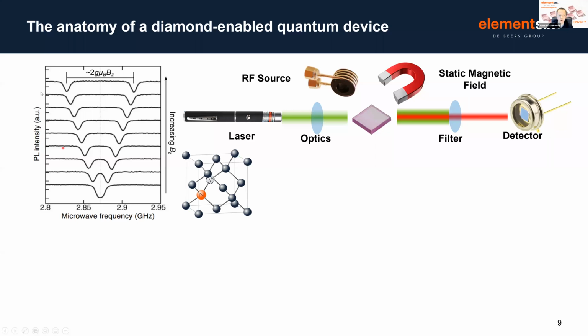And we can do this by this schematic that I show on the top left-hand side of this slide, using the electronic Zeeman interaction. So our plus and minus 1 spin levels in the ground state are split by the presence of a magnetic field that is along the NV axis of this particular NV defect. So then through the electronic Zeeman interaction, we observe a splitting in energy levels that is proportional to the magnitude of the magnetic field along that NV's symmetry axis.